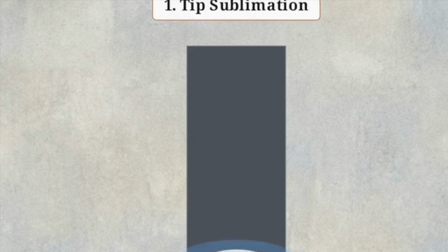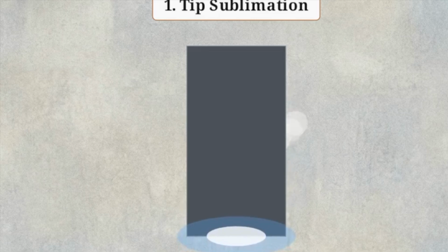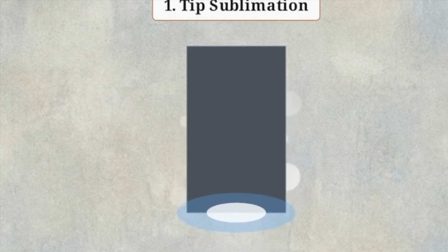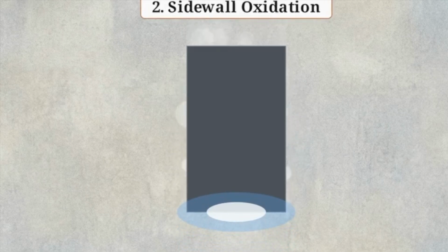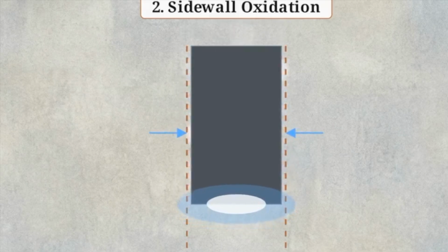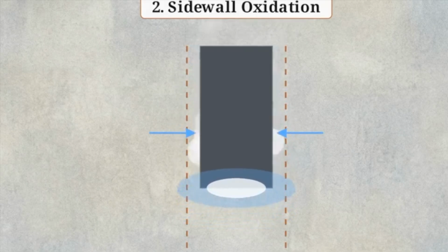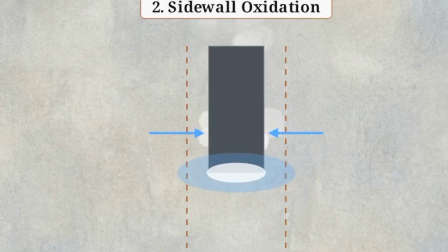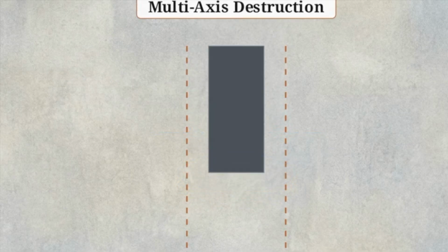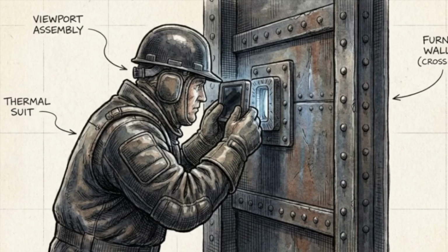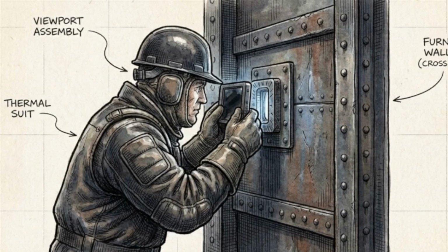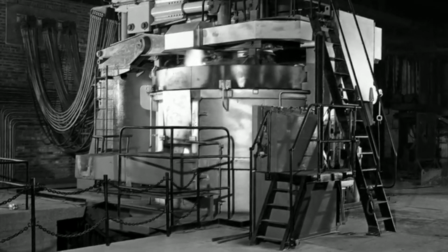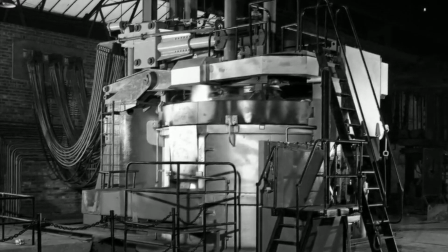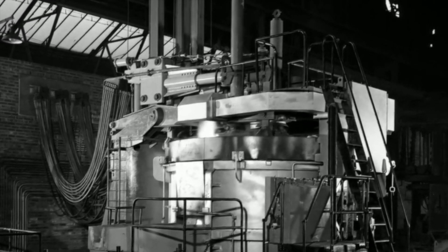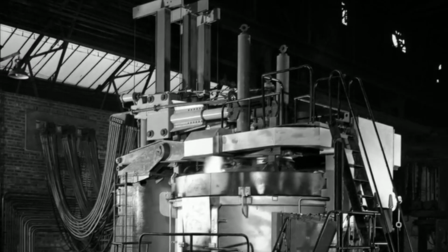First, tip sublimation. The arc's heat vaporizes solid graphite at the electrode's tip. Second, sidewall oxidation eats away the surface. Ambient heat and chemical exposure continuously erode the column's sides inward. Operators traditionally mitigate this wear through manual observation, but the scale and opacity of the heavy steel furnace shell make it impossible to see the active arc or adjust the columns in time.